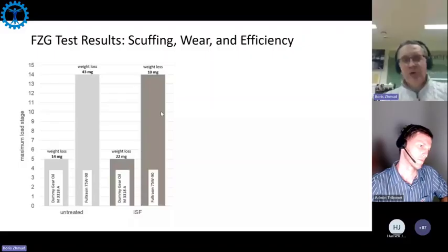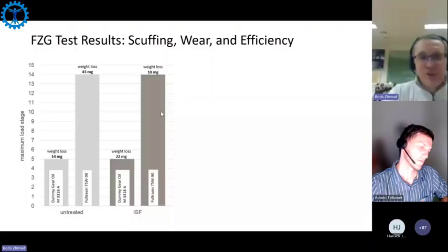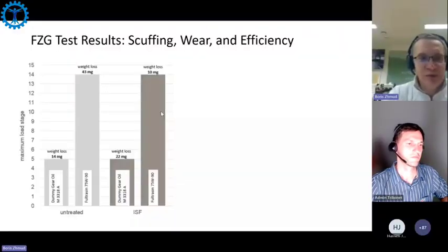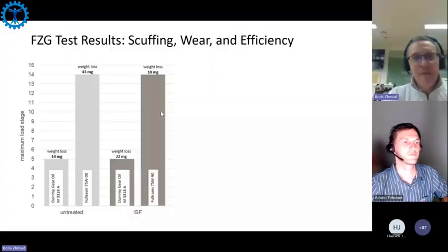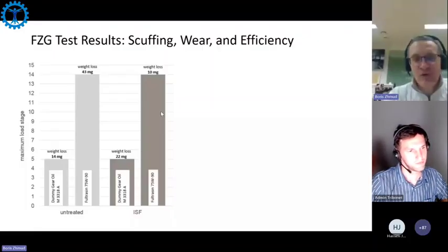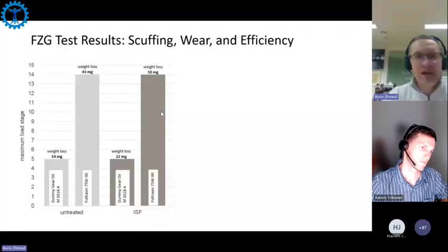of two different finishes with two different lubricants. One lubricant is a fully formulated lubricant with API GL-5 specification, which will go all the way up to load stage 14 without failure. On the right-hand side, the dark gray area shows super finished surfaces. On the left-hand side, you see how conventional ground surfaces behave.